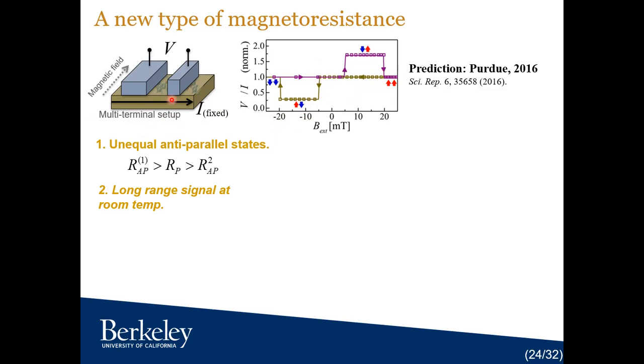So two major things about this prediction are that the anti-parallel states are symmetric around the parallel states, and that this effect is supposed to be long range. If we increase the distance between the contacts, this signal should not degrade, because this is new physics. This is way different from conventional magnetoresistance, where anti-parallel states are always higher than the parallel states, and the signal persists only up to a few nanometers of separation between the contacts.